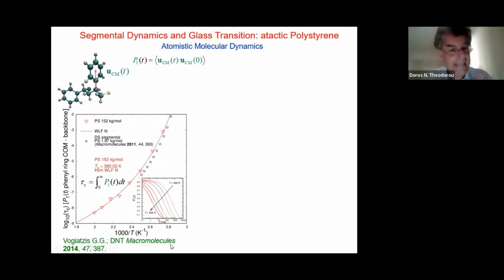Of course, even that is not possible for very long times, because you run out of computer time. So even this, you have to rely on a certain form of the correlation function. And typically, these correlation functions, P1 of t, are of a so-called modified KWW form. They are stretched exponentials. So essentially, you can fit a stretched exponential to whatever part of this function you can get out of the molecular dynamics simulations. These are the bolder parts that are shown here. And then the rest is really extrapolation based on the KWW expression.